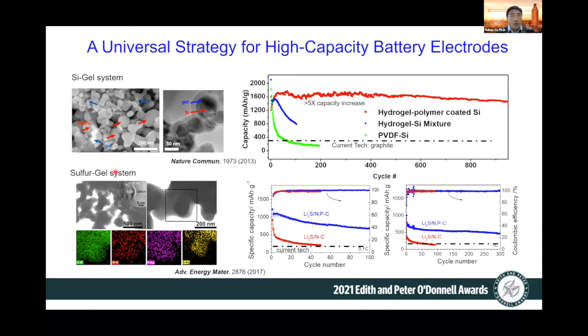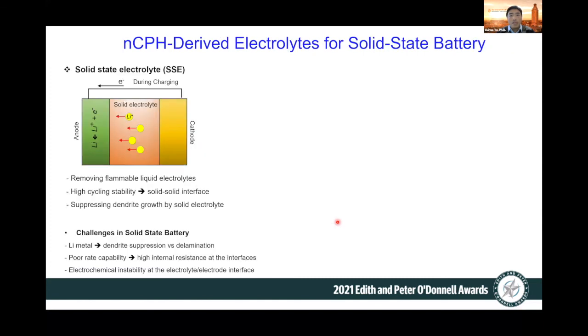The same applies to the cathode. As future generation cathode materials, they also have high theoretical capacity. So we use the gel to combine with lithium sulfide and sulfur, and they can work very stably. And then another example I'd like to show is for solid state batteries.